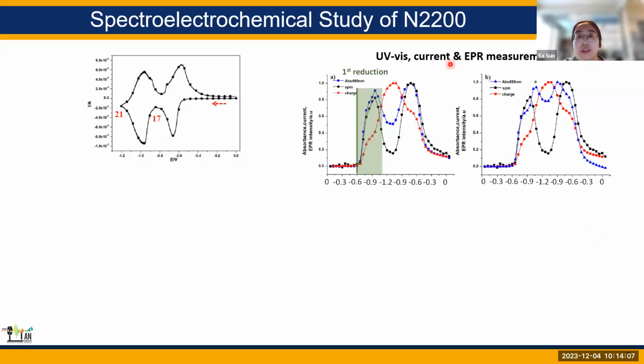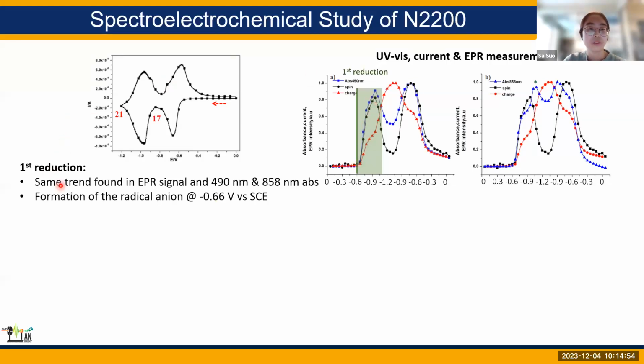So to better understand this data, they conducted the EPR measurement and compared it along with the UV and current data. So the top two panels show the first reduction process. Basically they pick the two growing absorptions at 490 and 858. We can actually just look at this spectra, for example. When the current grows up, where the first reduction happens, we can see that the absorption grows concurrent with the spin growing from 0 to 1. So since the EPR signal has the same trend as the increasing absorption, they think this is the evidence of formation of the radical anion at the first reduction.